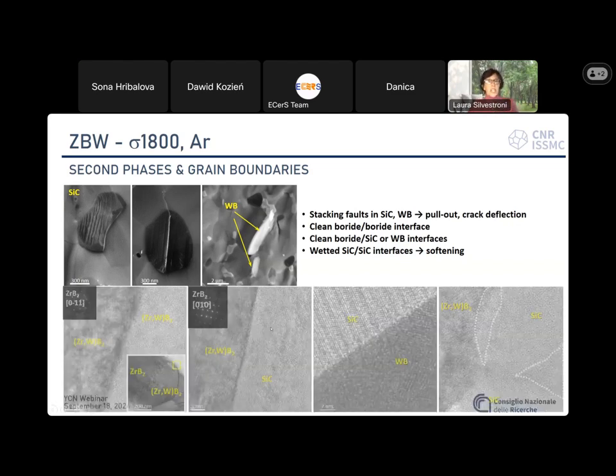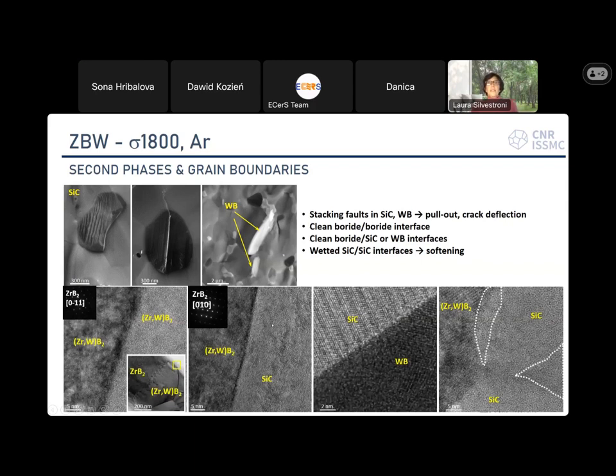The grain junctions remained clean, like in the as-sintered material, except where we had two adjacent silicon carbide grains, in this region, where we observed some glass between the two. So the choice of adding just a little bit of silicon carbide was good in avoiding creep at high temperature.